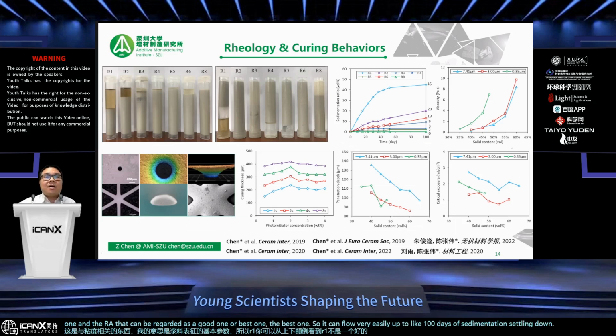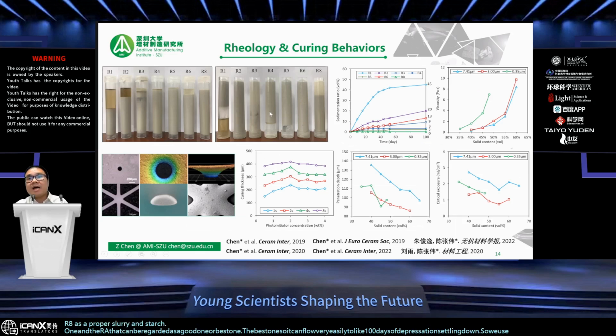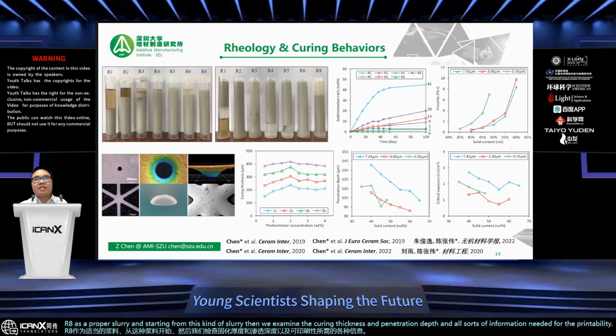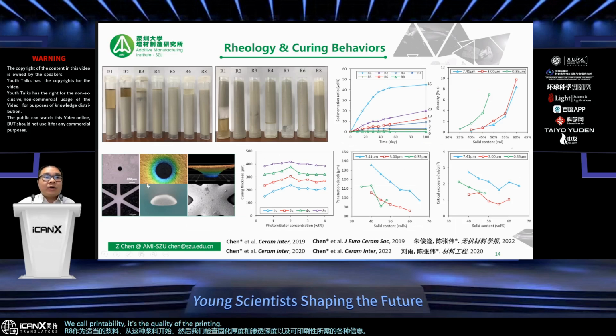So we use R8 as a proper slurry, and starting from this slurry, we examine the curing thickness, penetration depths, and all sorts of information needed for printability. We call printability the quality of the printing, and the quality of printing includes the single units, like holes, single lines, single walls, thickness, and layers as well. So if everything's good, then we start printing.